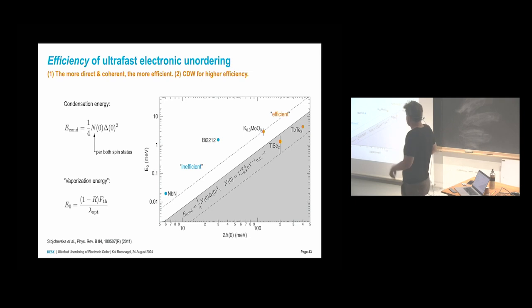Okay, and then I should finally come to the efficiency. I compare the efficiency of switching. One measure, and this was also done by Dragan Mihailovic in this very early paper, where they compared the condensation energy of your charge density wave or superconducting state, which is related to the density of states at the Fermi level and the gap size, and compared it to the energy that you deposit by optical excitation in your system, what they call the vaporization energy. Here again for our systems, and here's this condensation line with some error bars because I do not find so reliable values for the density of states.